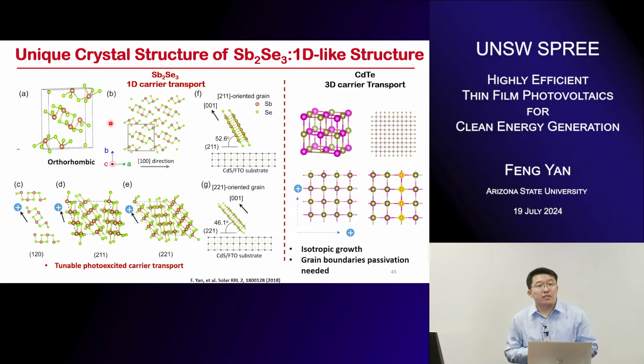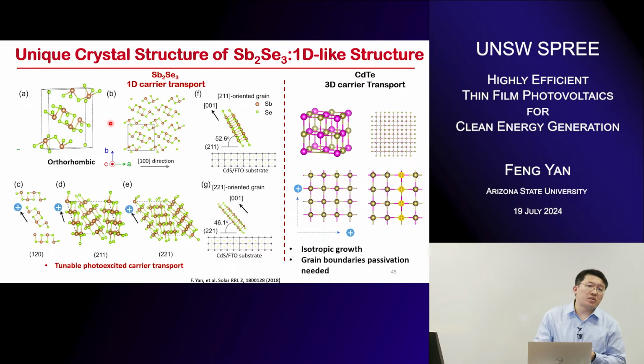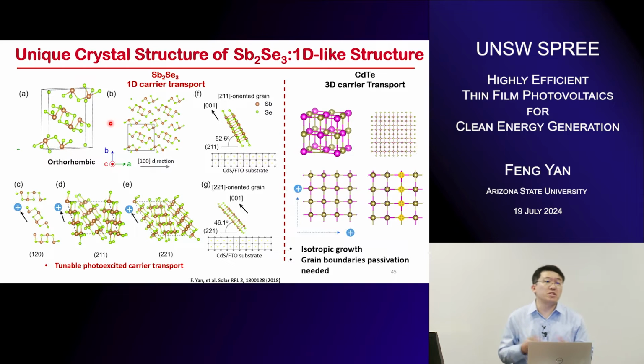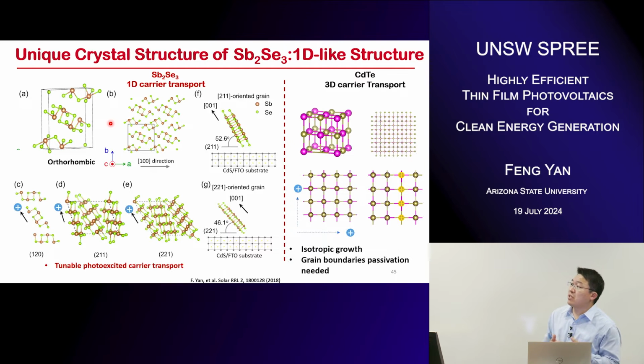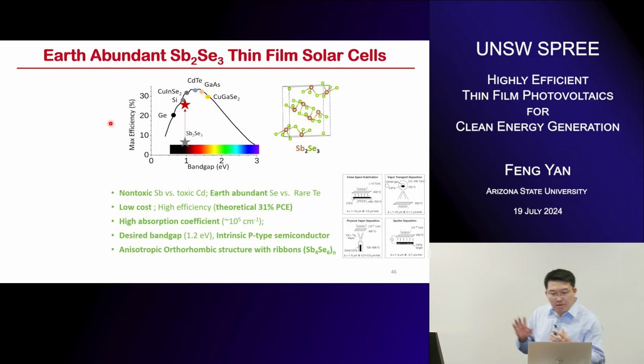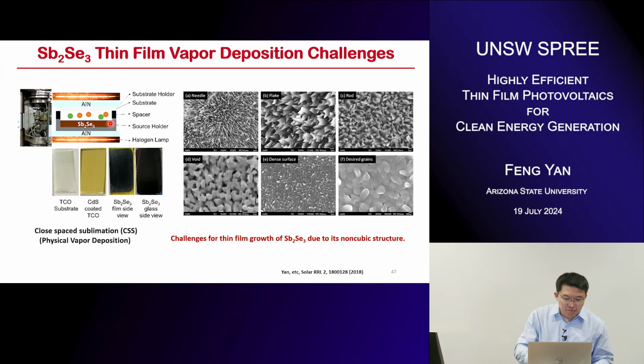But the difference is the unique crystalline structure of the antimony selenide, which is a one-dimensional ribbon structure. So this creates some challenges to grow this film like the cadmium telluride, because cadmium telluride is pretty much 3D cubic, so there are fewer limits to growing this film as a high-quality material. And we tried to grow this one, and based on this technique, we evaluated the growth. It seemed like a very promising candidate to bridge the gap between cadmium telluride and low-toxic, earth-abundant material. But it's pretty challenging.